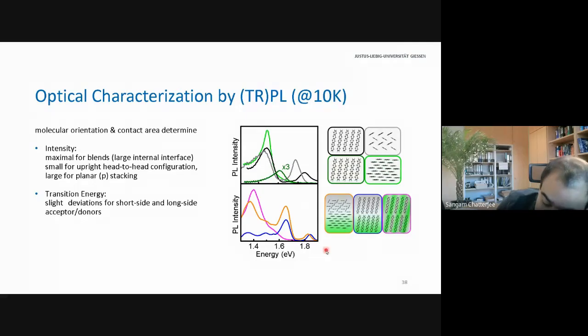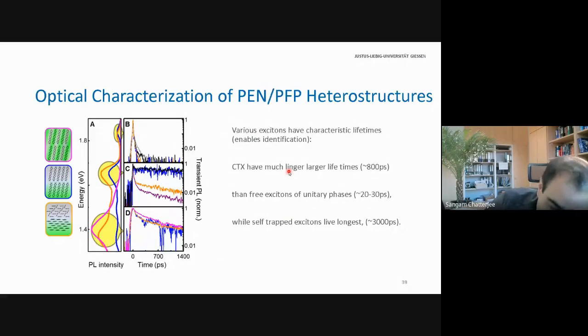And when you look at the emission spectra, you see that while the regular emission is at 1.5 to 1.8 eV, you see more pronounced emission at lower energies for the charge transfer structures, and it's most pronounced for the purple or the intermixed structure, which is also not too surprising. This could be remnants of one of the resonances that you find here, which might be due to the fact that you have two big bulk systems sitting here, but it's only one of the two resonances you have up here. It's not both.